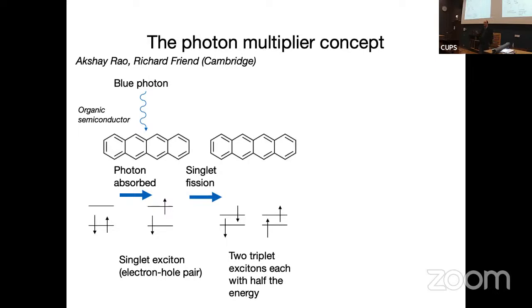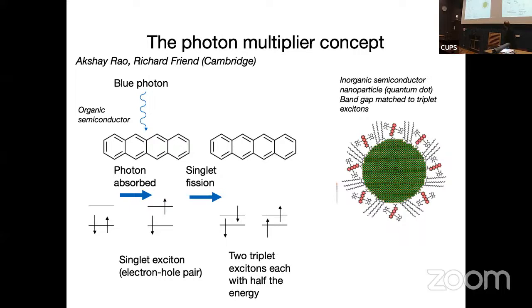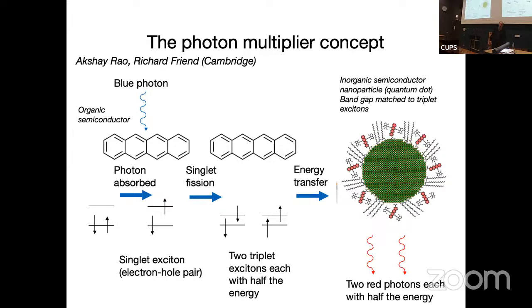But the concept that Akshay came up with was, if you have an inorganic semiconductor nanoparticle, otherwise known as a quantum dot, and you match the band gap to the triplet excitons, then these triplet excitons can hop across into the quantum dot. You can control the band gap of the quantum dot precisely by changing its size. And then the dot will kick out two red photons, each with half the energy. So this is a marvelous scheme in which, in principle, every step is 100% efficient. So this ought to work.